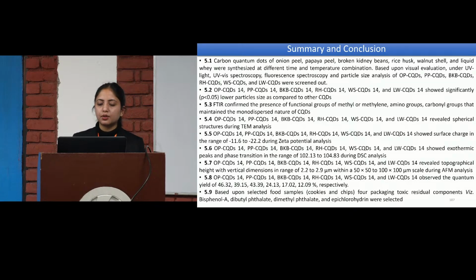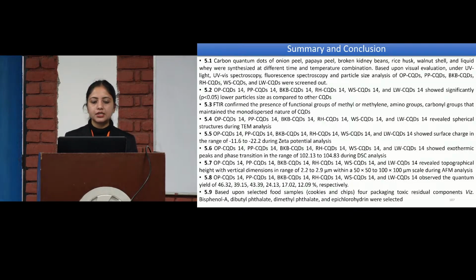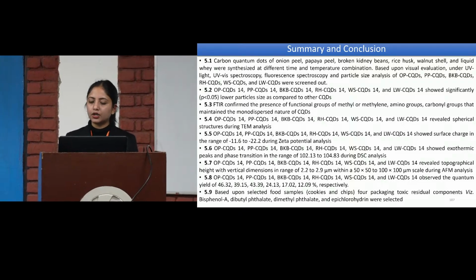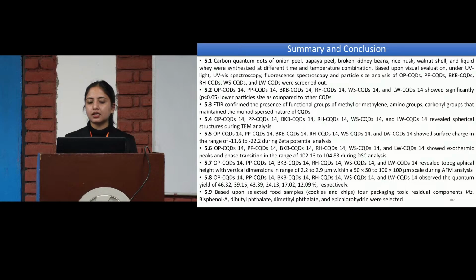Then this is the summary. I'll summarize my research work. Firstly, we synthesized carbon quantum dots from onion peel, papaya peel, broken kidney beans, rice husk, walnut shell, and liquid whey at different time and temperature combinations. Based upon the visual evaluation under the UV light, UV spectra, fluorescence spectroscopy, and particle size analysis, the carbon quantum dots were screened. After that, the onion peel, papaya peel, broken kidney bean, rice husk, walnut, and liquid whey carbon dots at 200 degrees Celsius for 10 hours showed significantly lower particle size compared to the other carbon dots.